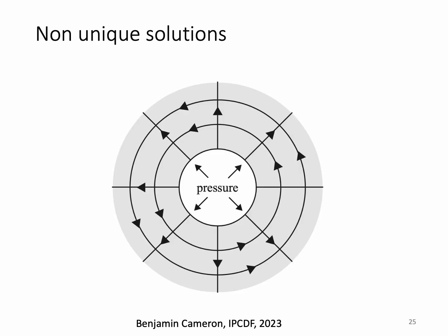Sometimes, for some problems, imagine a pipe with a thick-walled cylinder with a pressure inside. You have these characteristic loops going around the circumference. Here, this actually gives rise to non-unique solutions to the equation, so you can't really solve them. And this is because there's nowhere to start the calculation when the characteristic lines form closed loops. So this is a problem.